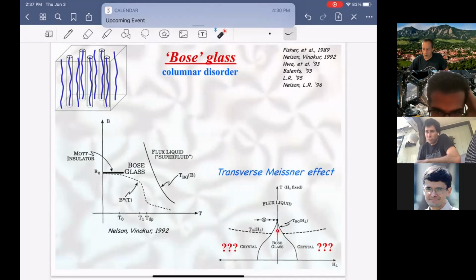And what they discovered is, not surprisingly, if you understand Bose glasses in a quantum context, that the state is actually stable up to a critical value of the tilt angle or transverse field. And so they call this a transverse Meissner effect. Namely, the Bose glass phase excludes transverse field or tilting of the field. And that's easy to understand qualitatively. Simply, vortices are stuck on these columnar defects. And so when you try to tilt them, they resist.